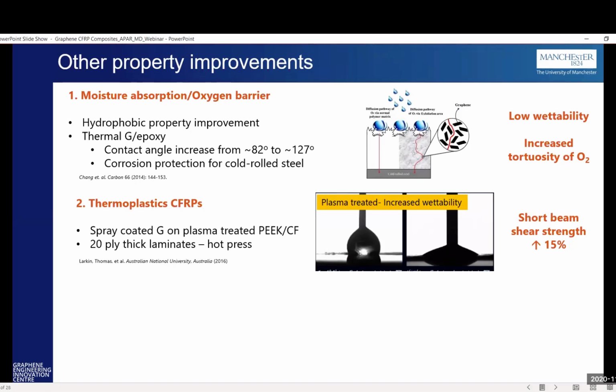What they have done is surface modify it using a plasma to increase the adhesion of this graphene. And they were able to hot press these laminates together. These are already high performing laminates, but they showed an improvement of the short beam shear strength by 15%. So there's still a lot of development that can happen even within already high performing materials.